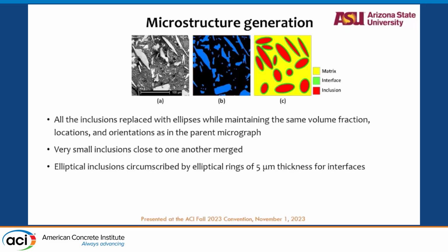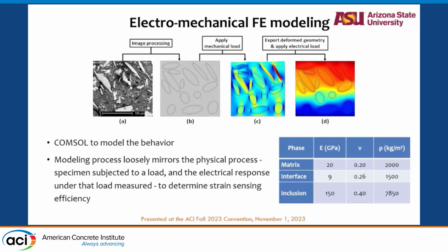The thing we observed is that when we acted a stress upon it, the model was acted on by a mechanical load. We saw that the sudden change in the interface also caused the model to have voids and see stray currents on the section. So what we had to do was introduce cohesive zone parameters.